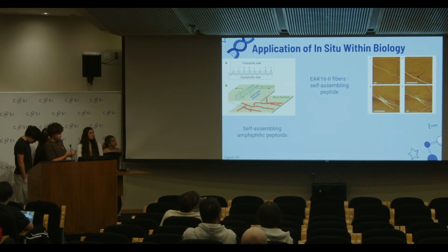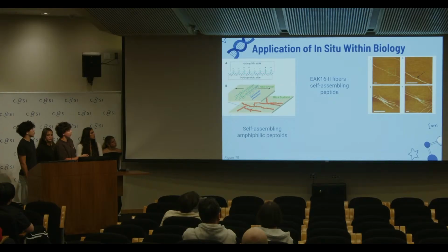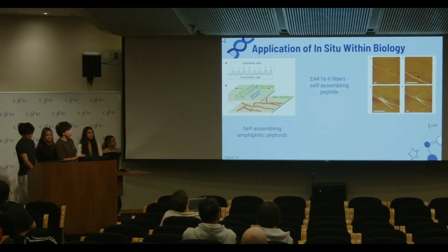In figures C and D, it's kind of hard to see, but there's a small little fragment that has broken off by using the atomic force microscope probe. So we're using mechanical force. In E and F, you can see that it's slowly growing back, and we can see that using high-speed AFM.